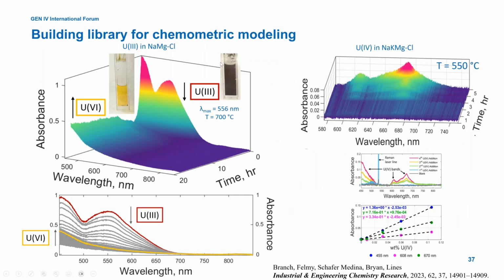The first slide here is showing the building of the library, or the chemometric library, the training set library that we need to go ahead and then measure uranium different oxidation states in some of these solutions. And this shows a picture of the uranium-3 in one of our cuvettes. This is a molten salt system at 700 degrees Celsius. This shows the photograph of the uranium-6 in solution. And we measured variable concentrations of uranium-4, 6 mixtures. We also measure variable uranium-4 in different eutectic chloride melts. This shows some of the variable absorbance measurements that we use for our training set.